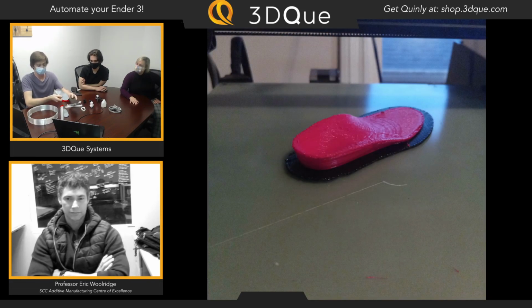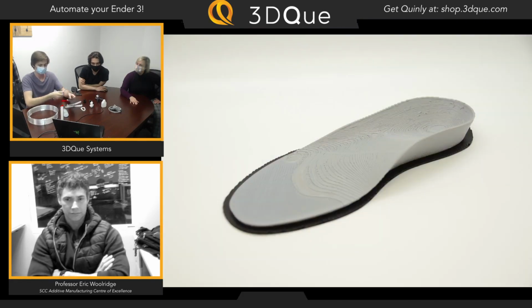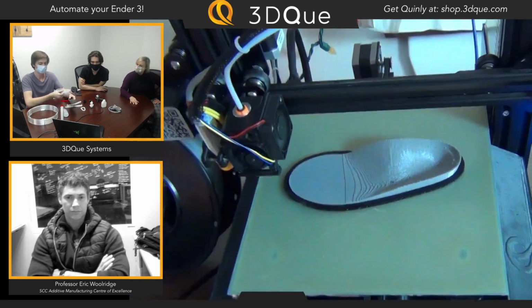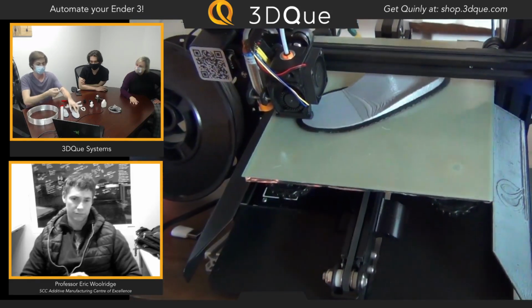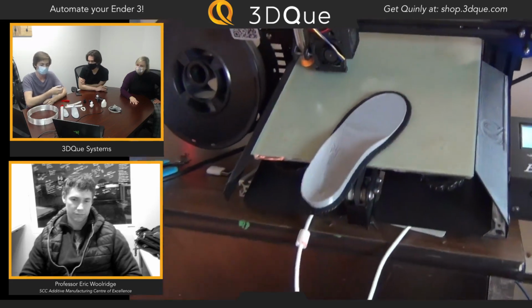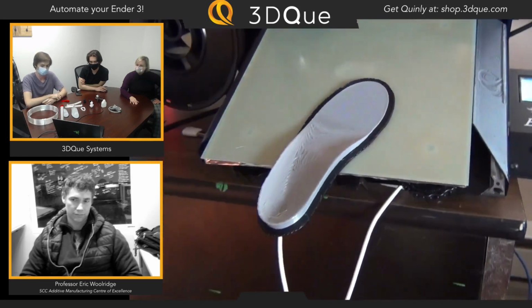So what I've been doing, this is more of just a proof of concept. It's not an automated technique yet, but printing a raft in PLA. And then in my slicer, I set a pause at my first layer so I could change the material to TPU. Then it would just finish the rest of the print in TPU. You can see the part being released here. It's not sticking. It just released completely. It looks like I just put the part there, but trust me, it was printed in place like that.